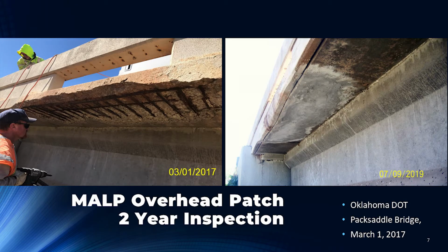The unique aspect here is that typically you do have to sandblast the rebar and treat it. Here, there's no sandblasting. It was installed by the Oklahoma DOT Bridge Maintenance Crew, and we continue to monitor it to this day. This was performed in March 2017, and they had a reinspection about 2.5 years later, in July of 2019. There was some hairline cracking. It was recently absorbed, but the material was bonded, and there's no evidence of corrosion.